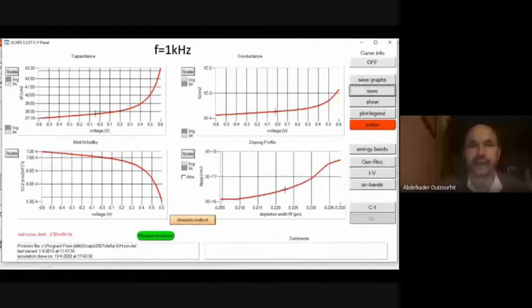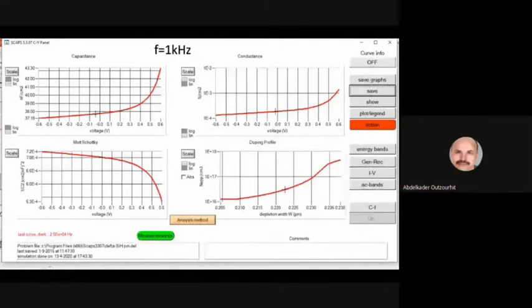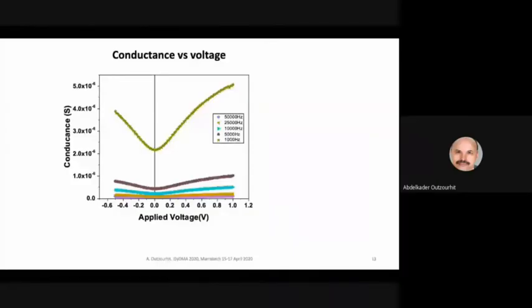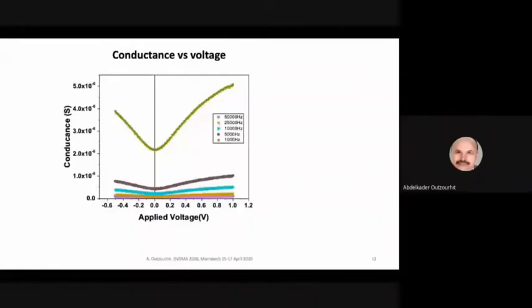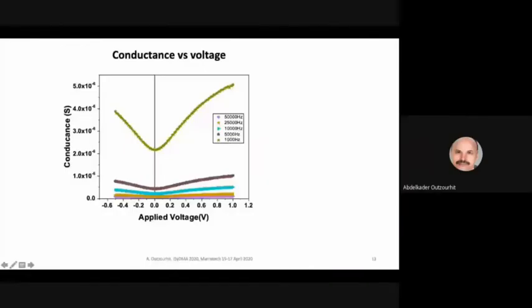These are the experimental values of the measurements of the conductance. As you can see, the conductance versus voltage is rather asymmetrical due to the rectifying nature of the IV characteristic of the cell, and also the changes of the conductance with bias are decreased as the measurement frequency increases. As you can see, if you go from the top here to the lower curve, the changes in the conductance become smaller in accordance also to the measurements in the capacitance.